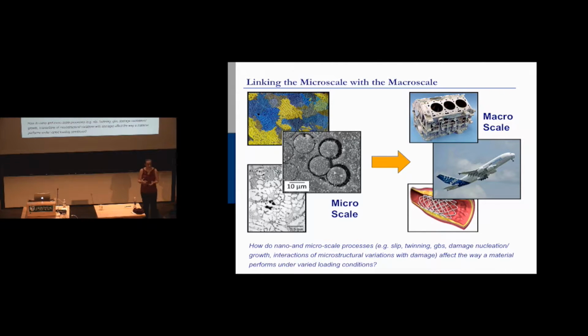One of the things we did, this is my collaboration with Wayne Jones, we took ultrasonic testing. There's a limited number of groups in the world that do this ultrasonic testing, where they take a specimen and put it in ultrasonic resonance at 20 kilohertz, so 20,000 times a second. You take a carrier specimen, you resonate it at 20,000 times a second, and you attach your specimen on for the ride. So now you're getting these very low loads, 20,000 times a second. And we needed to examine the effect of microstructure, so we needed to somehow port this inside of a scanning electron microscope so that we could load it at 20,000 times a second while watching the evolution of damage and the evolution of cracks with respect to the grains.